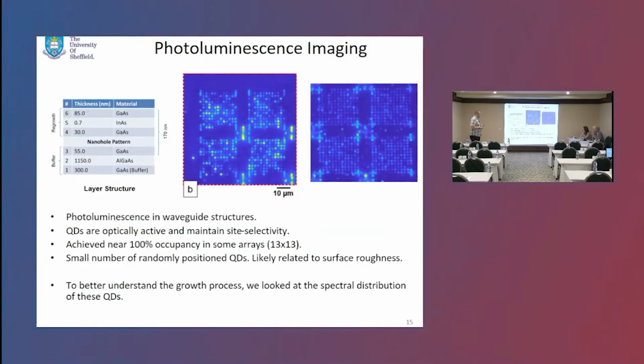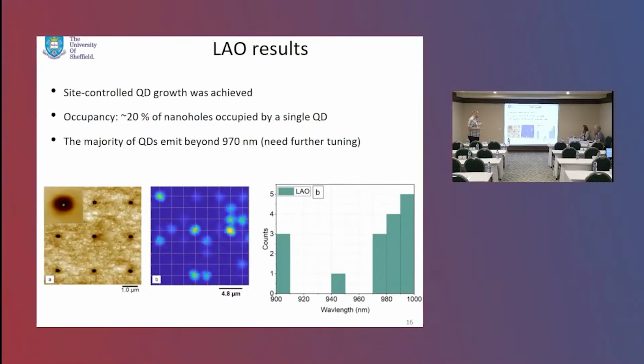So if we now compare two of the structures, this is an image from just a pure gallium arsenide sample with no buffer, and then this is from one of the waveguide structures. We can see that we're getting pretty good occupancy of the sites. In some of the arrays, we're achieving 100% occupancy in these 13 by 13 arrays. So to better understand what's going on, we've now looked at the spectral distribution of these dots. But we'll just jump and say, well, what about the LAO, which was the first thing we tried?